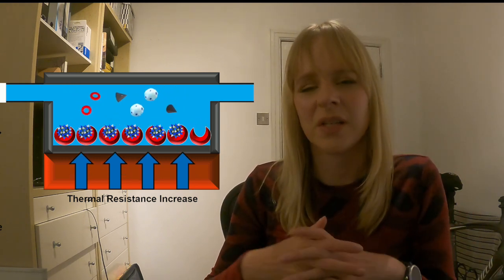And we are working here with 3D printed measurement cells, and the initial cells that we used still required a volume of 2 to 3 milliliters, which is quite high if you want to actually work with clinical samples. But within this project, we successfully managed to redesign them in order to work with samples as small as what you get from a normal swab from your nose.